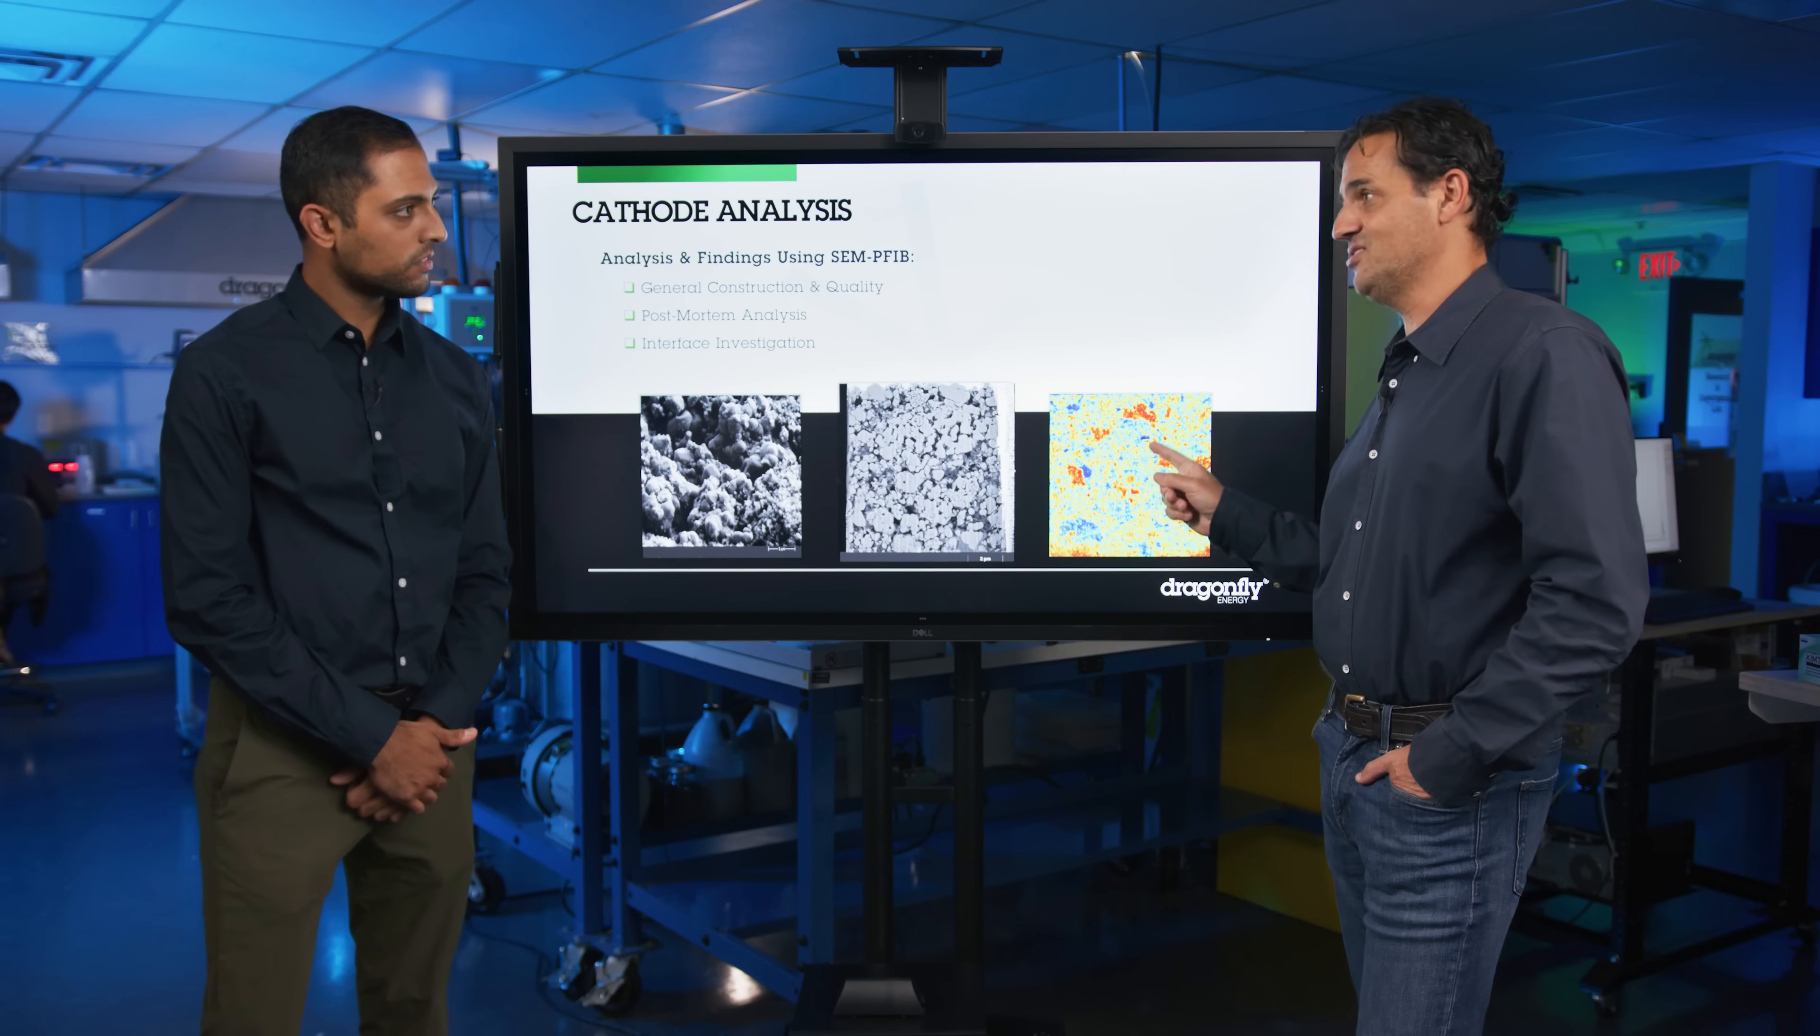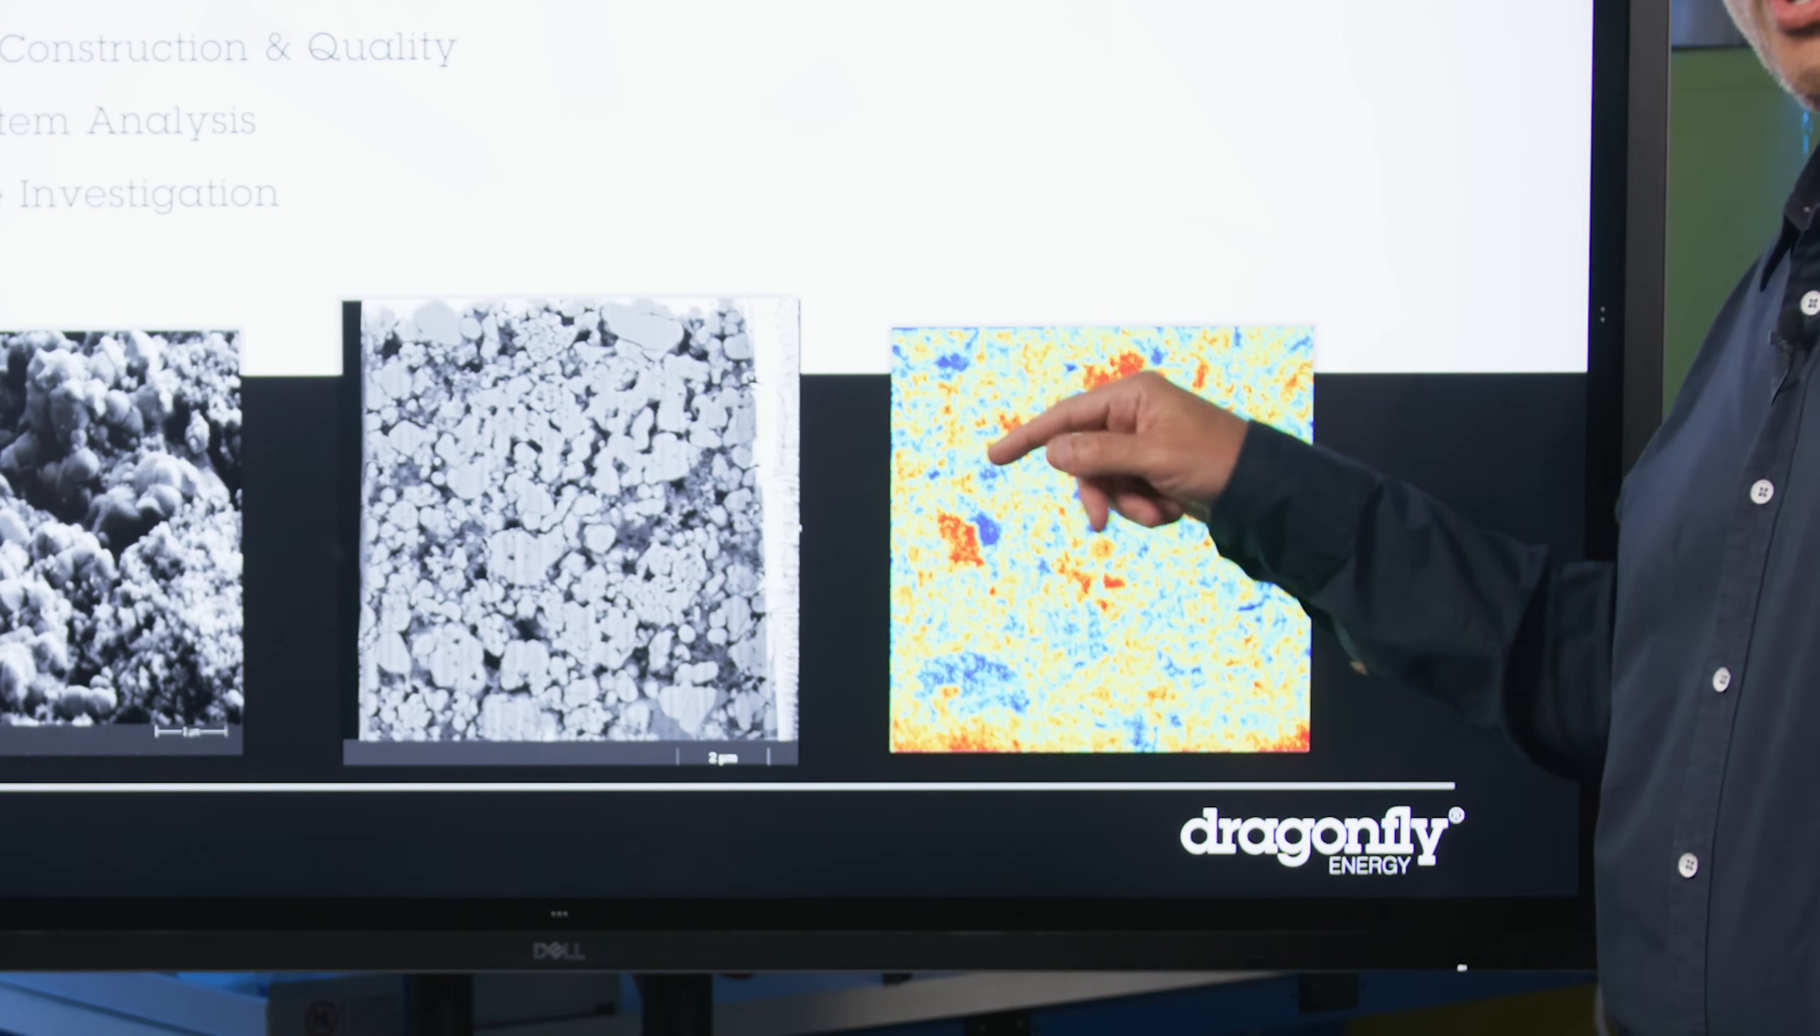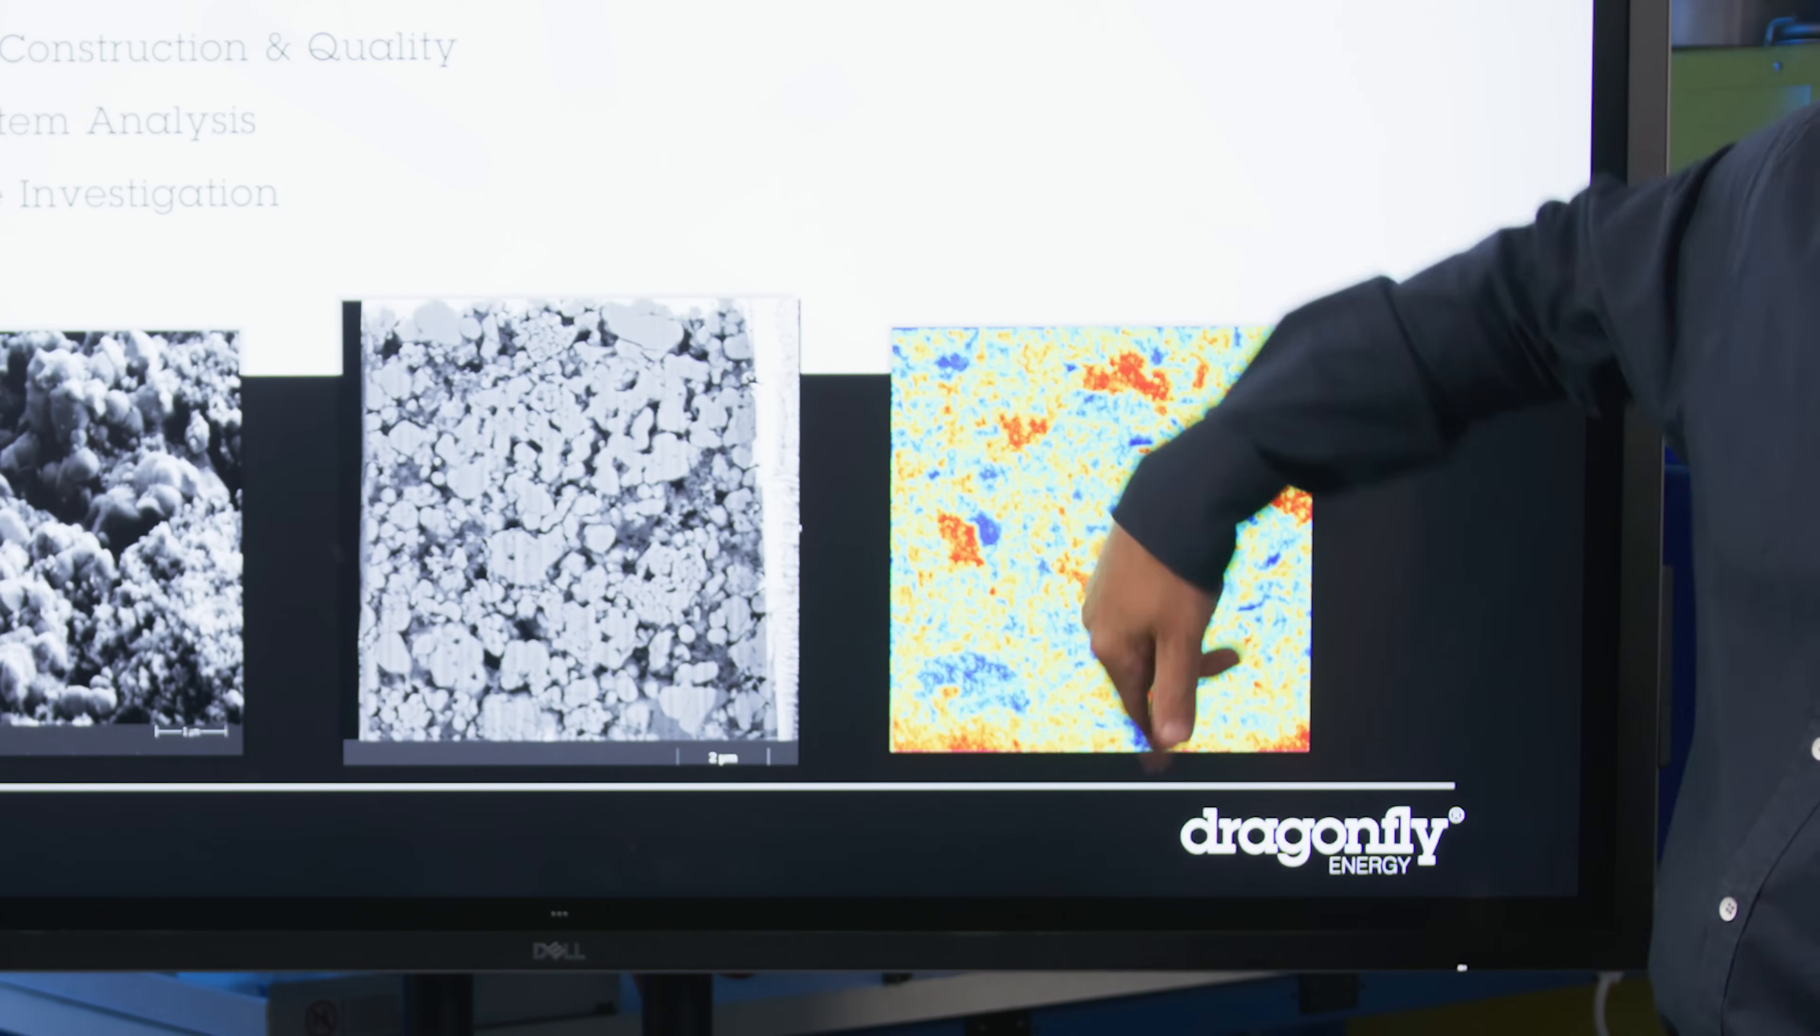And this image is awesome because this is a cross section. It was cut with an ion beam, so ions are cutting the cross section, and each time it makes a cut, you get all these molecules and ions fly off. And we take a what's called a time of flight mass spectrum, so we know what's in every pulse that comes off here.